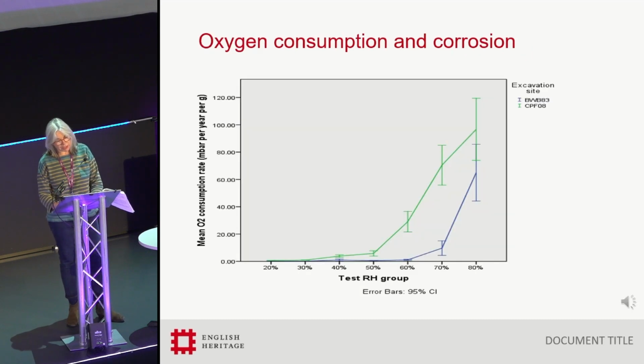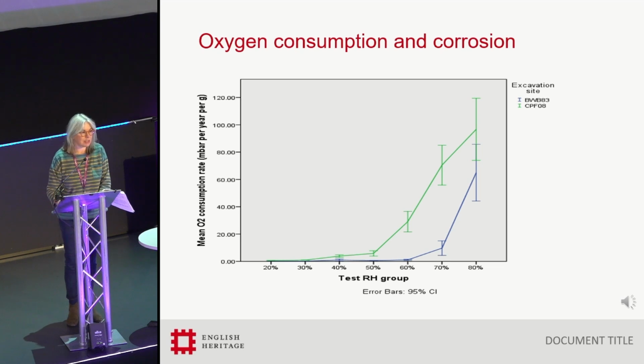This graph shows the changing corrosion rate with relative humidity amongst iron objects. Each point is a different batch of 8 to 12 objects, excavated from 2 sites. They're on the green and blue lines. Credit to David Watkinson at Cardiff University for this research. It shows oxygen consumption rate on the vertical axes and increasing RH on the horizontal. As you can see, the iron objects from one site, green, started to corrode in a small way at about 30%, and then in earnest at about 50% RH.